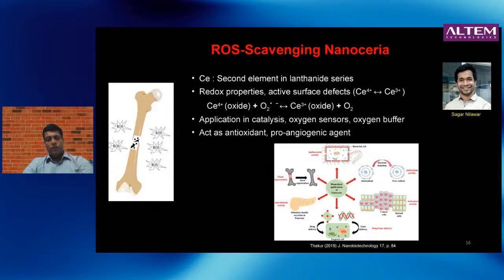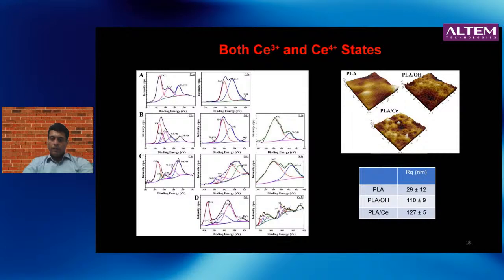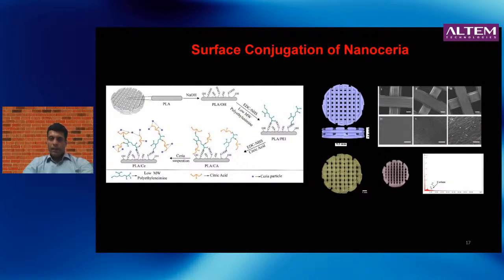So the idea was to see whether if you took a scaffold and modified it with Ceria, could it help in bone formation? Because the idea is that when there is new bone formation, there is a lot of ROS that is generated, and could you modulate that with nanoceria coated scaffolds? So what we've done here is take, again, the same idea, a scaffold of polylactic acid, modify it with citric acid, and then put it in a suspension of cerium oxide, and we get scaffolds that are decorated with cerium oxide particles, as you can see here.